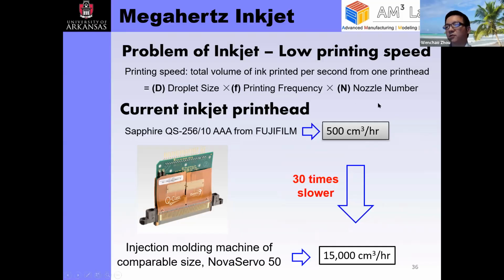The nozzle number is the primary way the industry has been used to speed up inkjet, and HP actually has the HP Moore's law to increase the inkjet printing speed. They double the printing speed every 18 or 24 months, primarily by doubling the number of nozzles in the printer, but there's only so much that you can pack into a printer head, because there's limited space and each nozzle has a certain size. The print head that has the highest number of nozzles is around 70,000 nozzles, which is a lot of nozzles, but that's approaching a limit. You can't do much more nowadays. There's also the printing frequency, which is the primary way that we're going to try to improve.